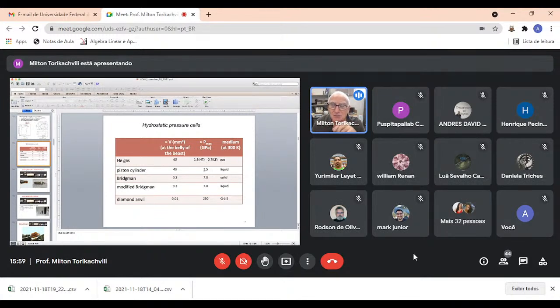Then there's the piston cylinder cell, the type that we use in my lab. You can go up to 2.5 gigapascal. They are good. They're somewhat easy to operate. There's good thermal stability for the sample. The sample volume is very large, so you can do very large things in it. Then there's the Bridgman cell. When you go from the piston cylinder cell to the Bridgman cell, you're losing a factor of 10 or 15 in volume. Your sample becomes very small, but you can get to 7 gigapascal.